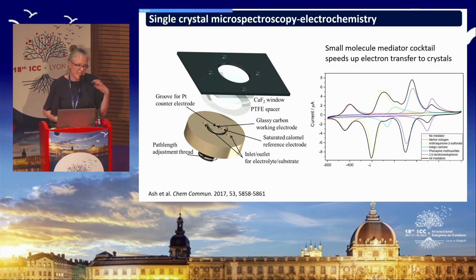We handle the crystal in its crystallization buffer, so the liquor that the crystal was formed within, and so it sits on the electrode in a little pool of that crystallization buffer in contact with a counter and reference electrode. And we add to the crystallization buffer a series of redox mediators which give us access to the whole potential range relevant to the experiment that we'd like to carry out. And so this is the electrochemistry of the series of mediator molecules that we've used here. In this case, they're all organic mediators, but to get down to lower potentials, we also sometimes use europium ligand complexes, which give us a nice range of tunable potentials in the more negative range.